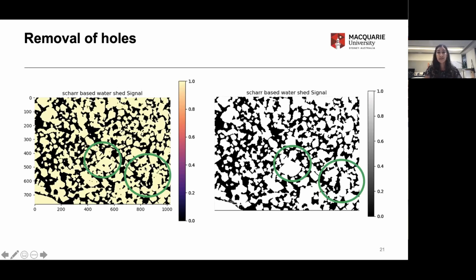This step is the only point in the whole segmentation workflow where the user has to make a decision. It's at this point that you can indicate grayscale intensity values which are at maximum or minimum grayscale intensities, and ask these to be removed. That does a really good job of closing up holes. If we look in these two green circles, you can see that I had holes previously in the middle of grains, and these have now been removed.